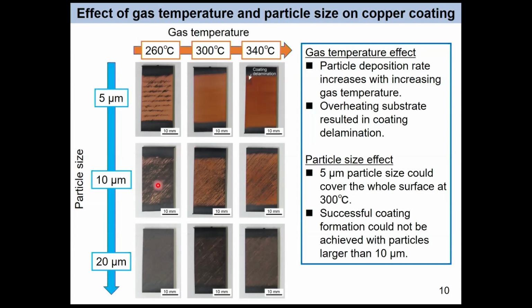The tendency is similar for 10 micron and 20 micron size particles; the deposition rate also increases. But in these cases, we cannot get continuous coating on the CFRP. When we focus on the particle size effect, 5 micron size could cover the whole surface at 300 degrees, and successful coating formation can be achieved. But with larger 10 micron and 20 micron particles, we cannot cover all surfaces on CFRP.